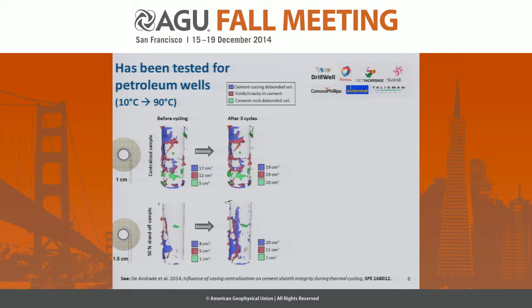So just to show you that this has been tested for the temperature range that we looked at, so 10 to 90 degrees, we have tested this setup. Here you see what is going on after 3 cycles. This is before cycling and after 3 cycles. And you see the volumes of each of the defect types that we've gone through here. And for the perfectly centralized casing, you see that very little is happening during cycling, at least for only these 3 cycles that we have tested so far.